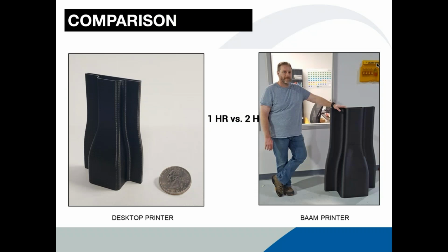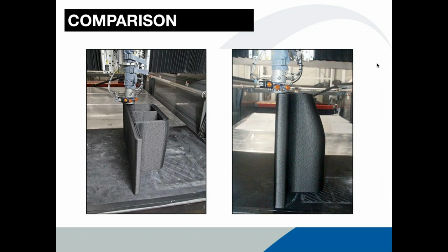So here's a great comparison here. On the left-hand side, and these are the two same exact parts, just one printed on a desktop printer and one printed on our BAAM. The one on the left took about an hour on the desktop printer. And you can see the size there with the quarter in the picture. And then on the right-hand side, this only took 2 hours, and it was about 100 pounds. And there's one of our engineers there, so you can get a sense of scale. So that's how fast we're printing. It's kind of an order of magnitude larger and faster. And there's the part being printed on our actual printer. We have a lot more pictures to show as we continue on.